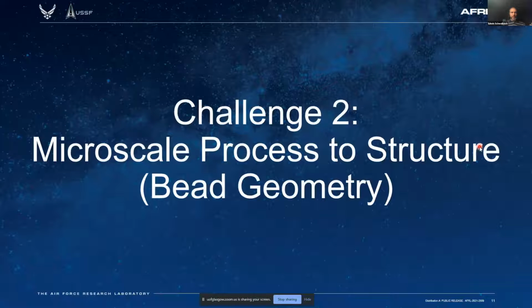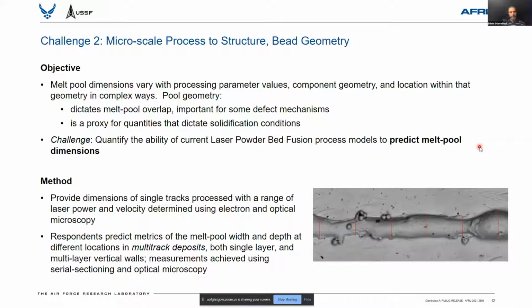So our second challenge, staying in this process to structure regime, but now thinking at a smaller length scale, we zeroed in on prediction of bead geometry as a first order indicator of some of the details of the thermal history. Again, the preceding talk gave a nice example of how complexities in the scan strategy can cause variations in the size and shape of the melt pools. And we thought looking at the ability to predict those shapes would be a good first proxy for getting ultimately towards a prediction of more details in the thermal histories.